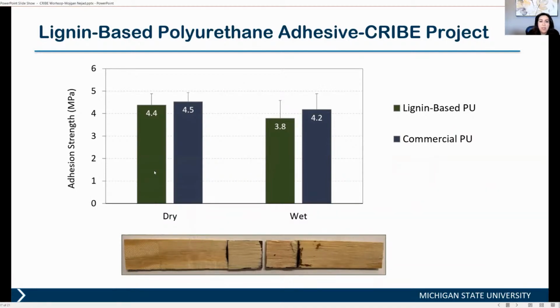This is a preliminary result that we have. The green bar shows the lignin-based polyurethane adhesives using kraft softwood lignin, and the blue is the commercially available adhesives currently used for CLT. This is a comparative analysis that we applied on veneer samples. The actual CLT test is different, but this is for comparing the two adhesives together. As you can see, we see significant, completely wood tear, and the lignin-based adhesives have similar dry and wet adhesion strengths to the commercial adhesives and perform really well. This is a formulation that we're going to work with Henkel to scale up production, using lignin at the commercial scale.